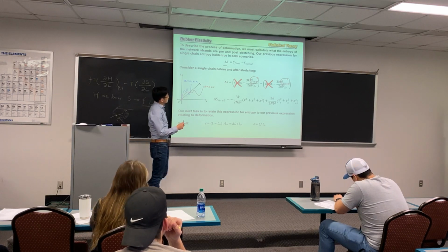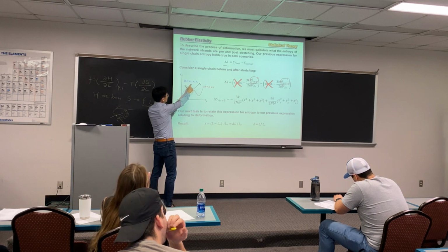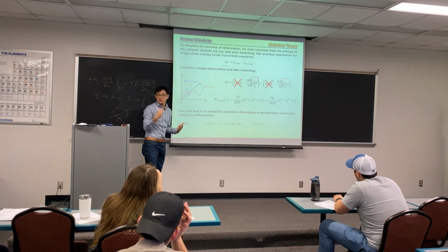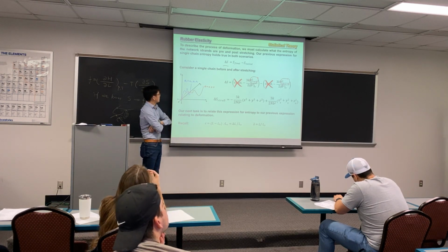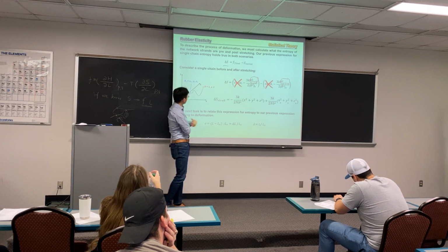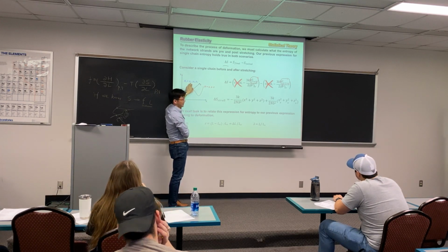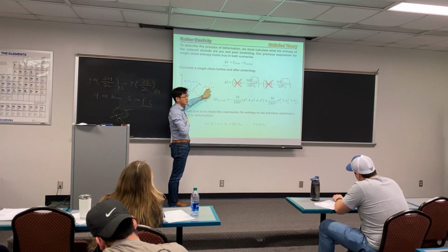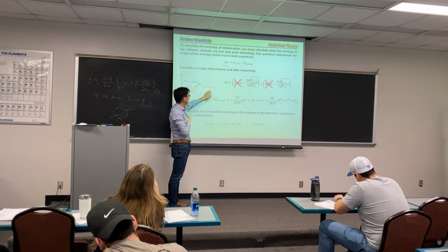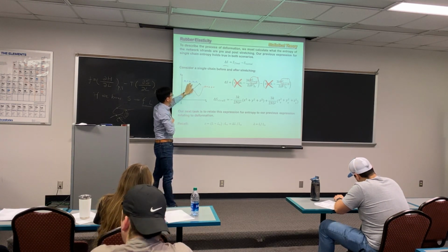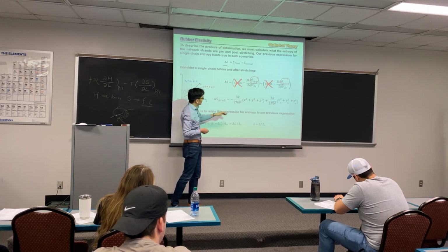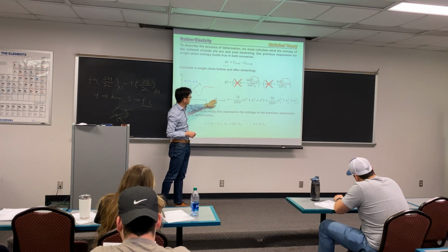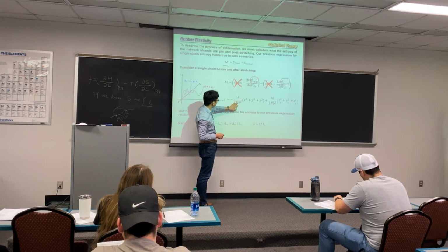So in three-dimensional space, R squared will equal x squared plus y squared plus z squared, right? If you have a three-dimensional axis, that's very easy to understand. We can apply the coordinates before and after. So after we stretch, we assume you have new coordinates x, y, z. Before you stretch, x0, y0, z0. If you apply that to the equation above, that's what you would get. The change in entropy from the strain will be equal to these two parameters.